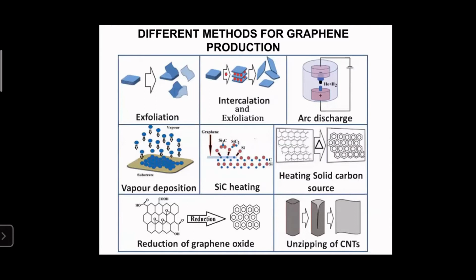And from graphite, by electric discharge and by electrochemical methods also, we can produce graphene. In the bottom-up method, chemical vapor deposition, silicon carbide heating, etc. produce high-quality graphene networks. But these methods are comparatively costly. Heating of solid carbon sources such as glucose in an inert atmosphere can produce graphene, and unzipping of carbon nanotubes can also result in the formation of graphene. But the large scale as well as commercial production of graphene is dependent on the reduction of graphene oxide.